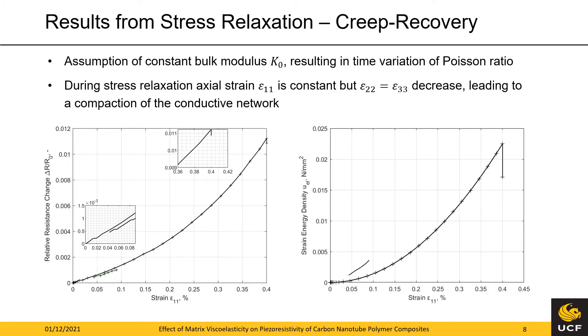On the left-hand side we see the relative resistance change over strain for the first load case and the assumption of a constant bulk modulus. The upper inset clearly shows the decrease of the resistance change as a vertical line during the stress relaxation where the axial strain is held constant. This behavior stems from the increasing compaction in the two transverse directions and indicates the loss of uniqueness in the relationship between relative resistance change and strain. The inset on the lower left shows the relative resistance change during the creep recovery step.